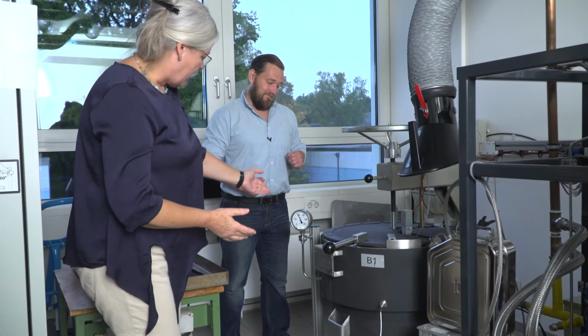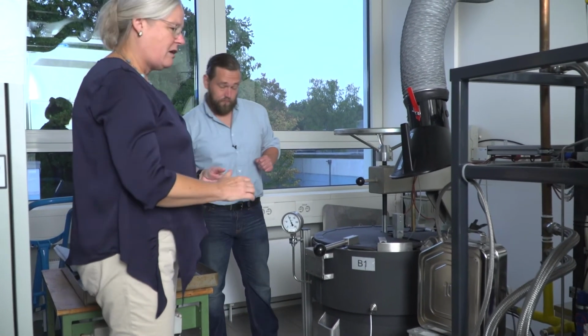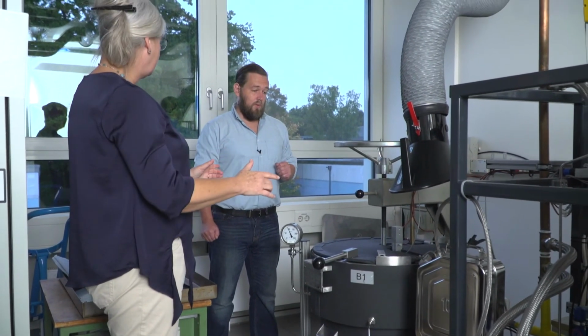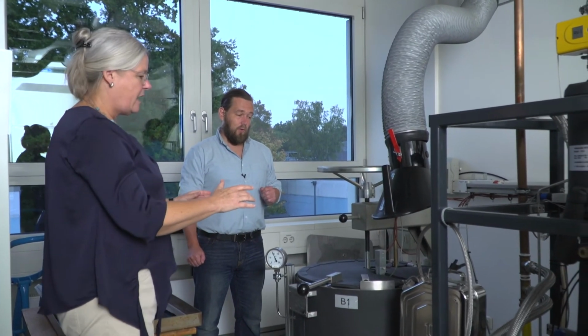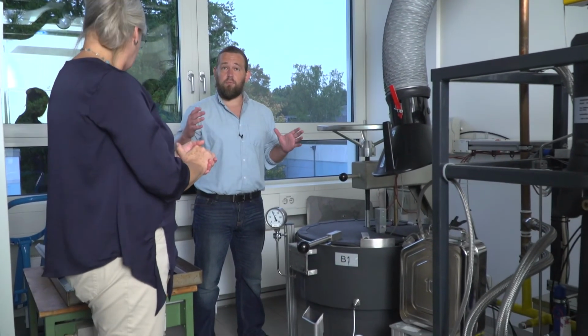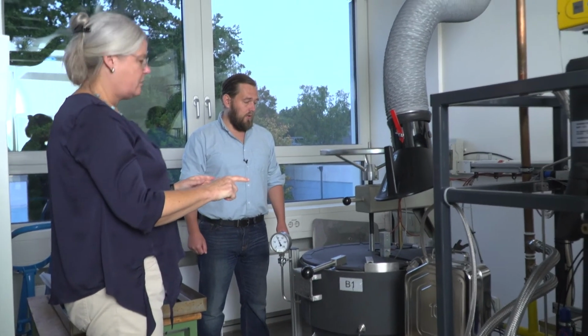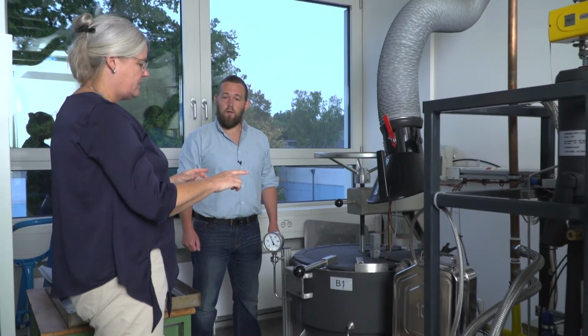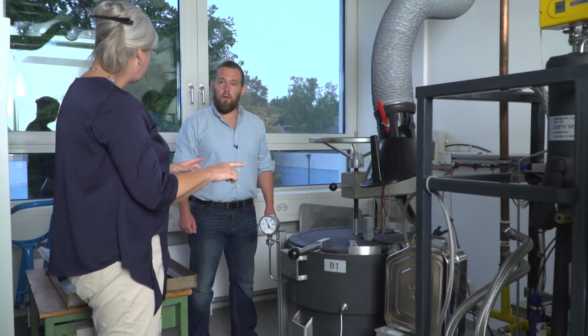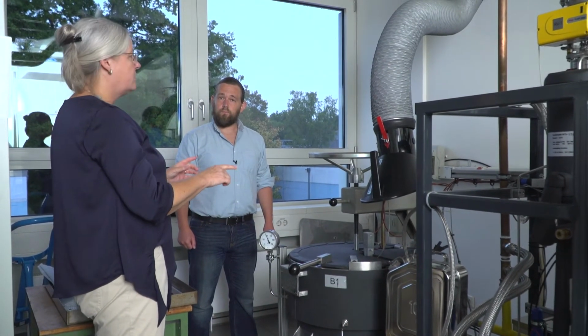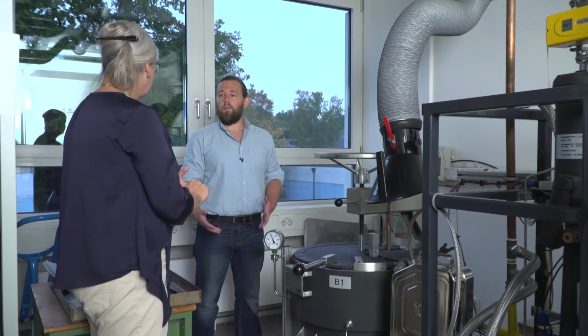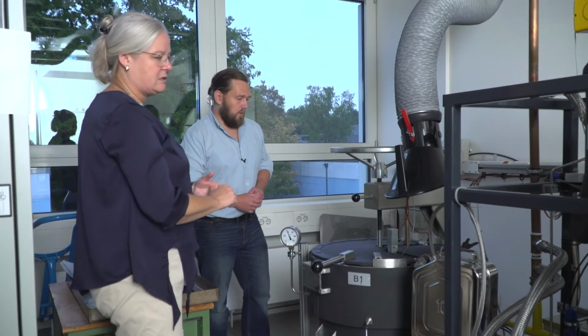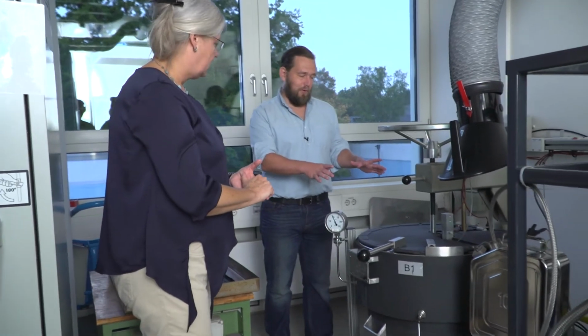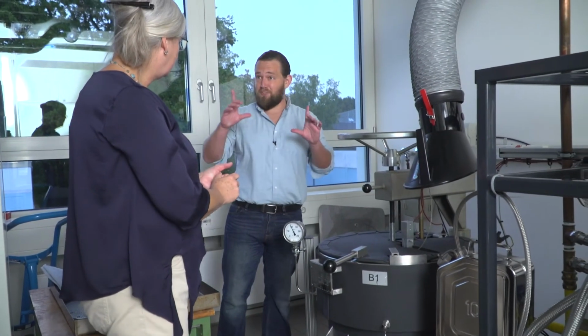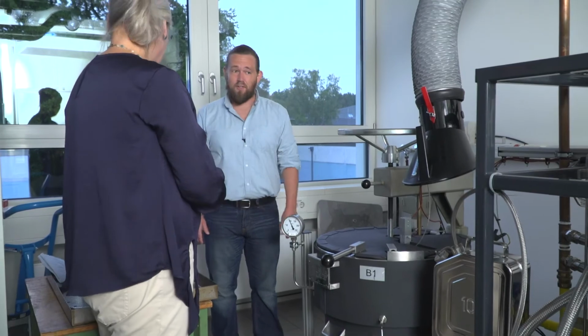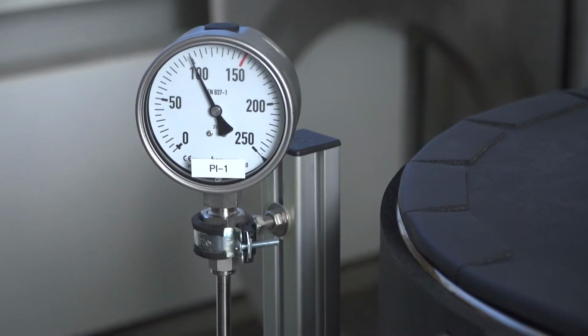And it's running. It's 100 bar inside. Oh boy. And we have a 50 centimeter diameter. Okay, 50 centimeters, about almost 2 feet, about 1.5 feet in English units. And you can make inside samples around 30 by 30 centimeters, because we would like to have a good measurement of thermal conductivity. That's about a foot by a foot for American viewers. That's a very nice sized aerogel monolith. That's about the biggest you ever really see in most cases.